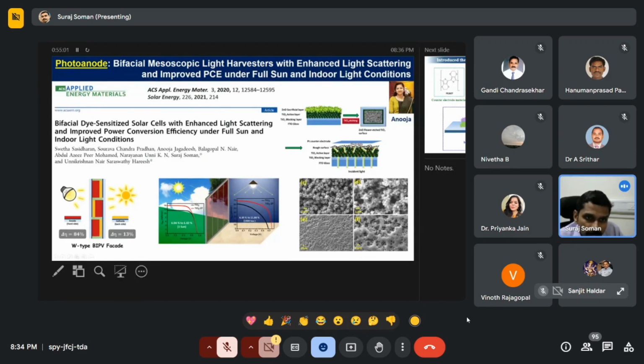One of my students, Anuja, made some microstructures with zinc oxide, star-shaped microstructures. She put those microstructures on top of the normal semiconductor. Then she used some acid treatment and removed those zinc oxide based microstructures. What you see here is those microstructures on top of TiO2, and once you remove them, you see these kinds of patterns on top of your conventional TiO2. This acts as scattering centers.